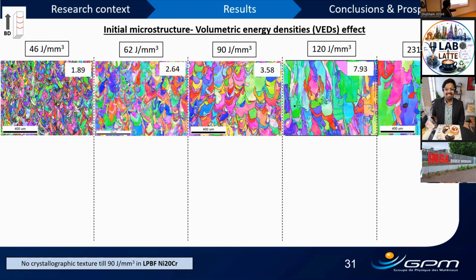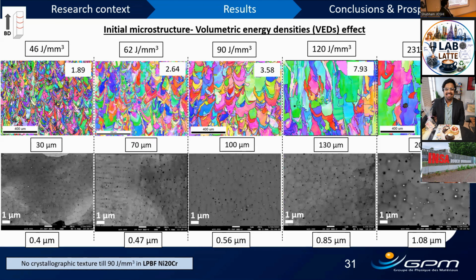So this was a sample. And with the range, we see that there is an increment in the maximum intensity of crystallographic textures. Up to 90 joules per millimeter cube, we do not have any crystallographic texture, but with 120 and 231, we can see the influence of texture. Also, average grain size seems to be increasing with increment in the volumetric energy density. Another aspect which changes with VED is the cell size or dendritic structure size. And we see that with increment in the VED, we also have increment in the cell size.